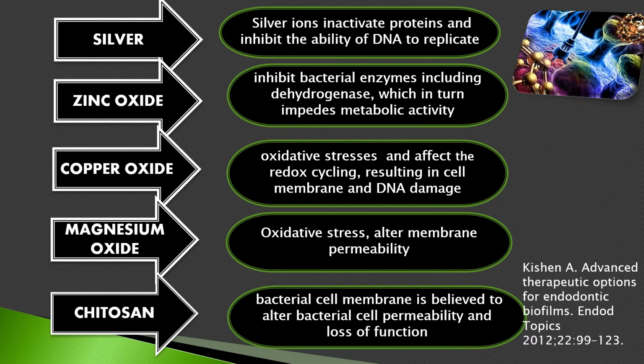Various nanoparticles exhibit various modes of action. Silver nanoparticles inactivate protein and inhibit the ability of DNA to replicate. Zinc oxide nanoparticles inhibit various bacterial enzymes, including dehydrogenase, which in turn impedes metabolic activity. Copper oxide nanoparticles cause oxidative stress and affect the redox cycling, resulting in cell membrane damage. Magnesium oxide nanoparticles also induce oxidative stress and alteration in membrane permeability, while chitosan nanoparticles alter the bacterial cell membrane, and it also results in the complete loss of the cell.